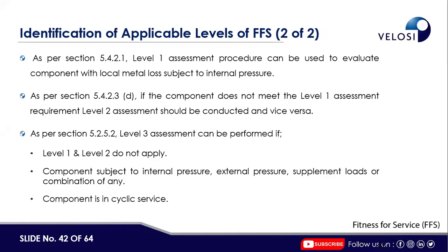As per section 5.4.2.1, the level 1 assessment procedure can be used to evaluate a component with local metal loss subject to internal pressure. As per section 5.4.2.3 D, if the component does not meet the level 1 assessment requirement, a level 2 assessment should be considered, and vice versa. As per section 5.2.5.2, a level 3 assessment can be performed. Level 1 and level 2 do not apply in case of the above section: component subject to internal pressure, external pressure, supplemental loads, or a combination of any. The component is in cyclic service, that's why level 3 is a must.